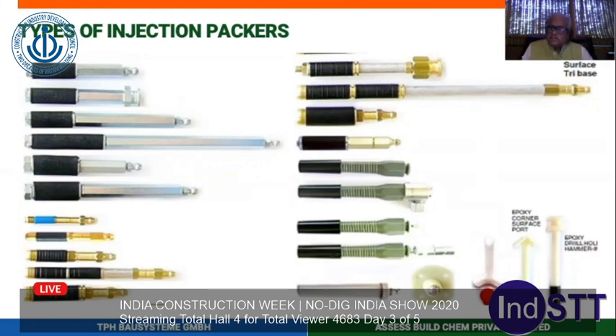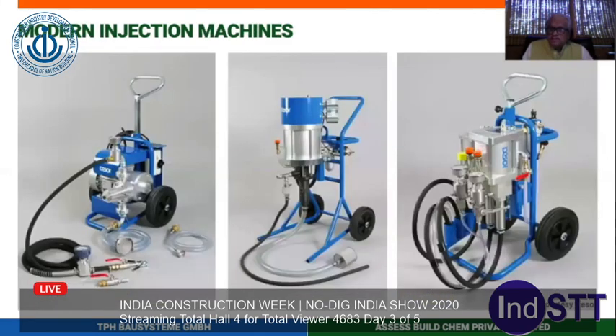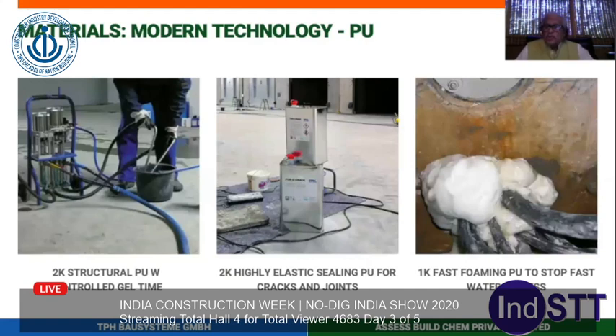What is most important about the connection is that the pressure that you put through machineries is not lost due to bad connections. You also require sophisticated machineries which are designed for this. For example, when you have a very small pot life injection, which has to react with each other within say a minute or less than a minute, or even a few seconds, like 10 seconds, then you need two component machineries. You cannot put both the materials in one component machinery. So you necessarily require two component machineries. Now these two component machineries, when you use polyurethanes, are sensitive to moisture. So these machineries should be so designed that there is no moisture penetrating. So polyurethanes is not the foams alone.